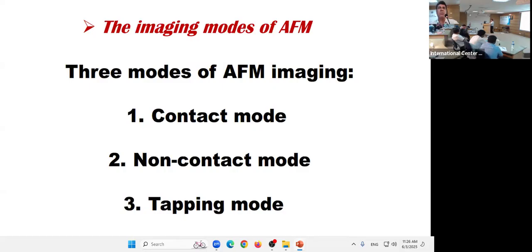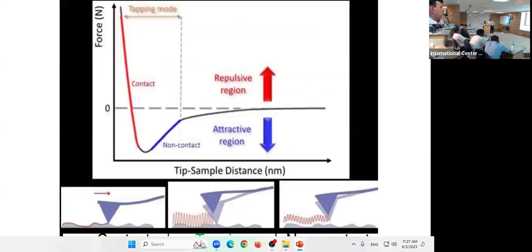The third one is the most widely used, the tapping mode. Mostly 90% of AFM images are recorded through tapping mode. The reason is that here you can generate a better quality image, and at the same time you do not disturb the morphology and the structures of the sample. So these are the three modes. In the contact mode, this is a flexible cantilever. It is just moving here, and when the laser is bombarded here, you see it coming up and down over the surface at the atomic level. The deflection of the light is different at different positions, and that creates the images.